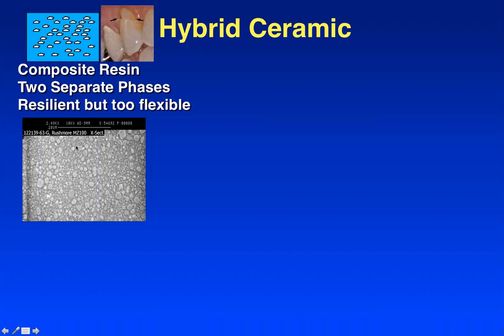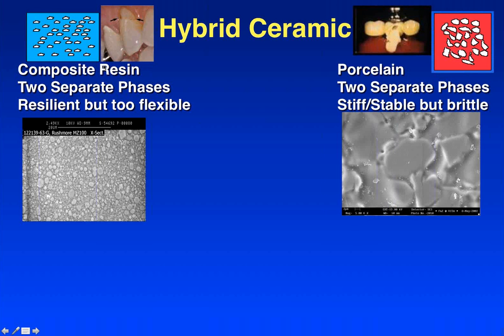Composite resins look like this. This is an MZ100 material, actually. These are various filler particles that are all surrounded by polymer. So your cartoon diagram, the little white things here are your filler particles. The blue is your polymer. Composite resins, 2 phases, separate phases, very resilient, flexible, too flexible, also tends to wear away. Ceramics, interestingly enough, if you look at the basic structure, looks very similar. Instead of having a polymer surrounding our crystal particles, we have a glass. Again, separate, discrete particles surrounded by glass. Very stable material, but too stiff, tends to fracture when it starts to move.